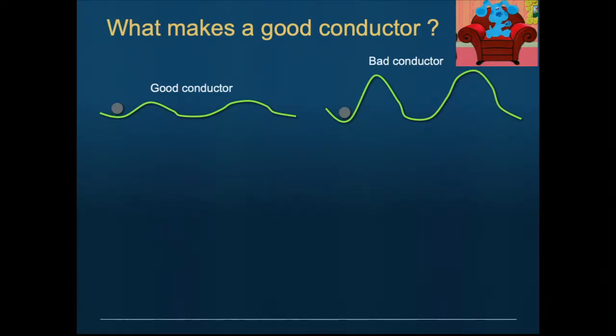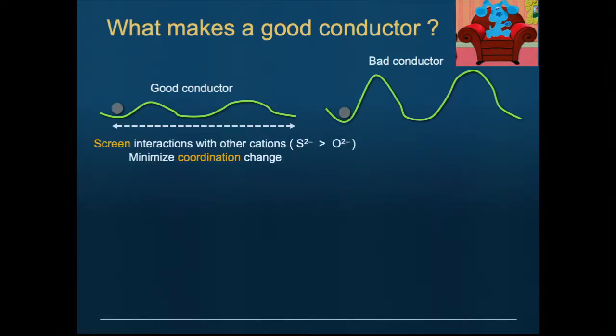Well, one way is, as this ion moves, you want to minimize the change of interaction with the rest of the structure. Because it's all about how flat the energy landscape is. So if you never change the interaction or have low interaction in general, then you can make a good conductor. So the first thing you do is you want to screen the interaction with the other cations, right? Because there are other cations around, they give you electrostatics.